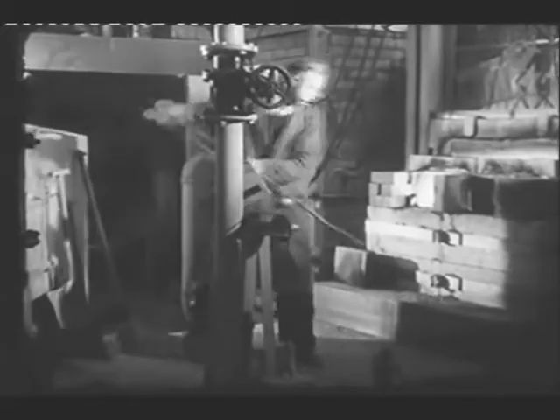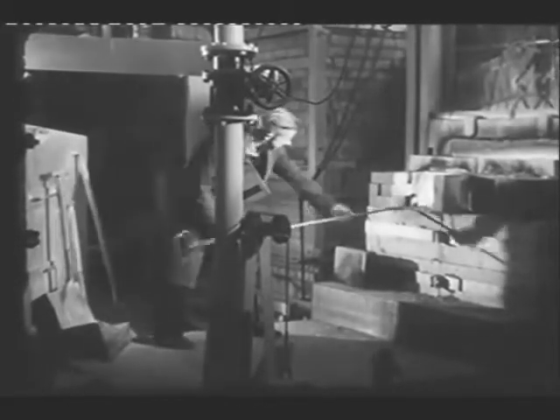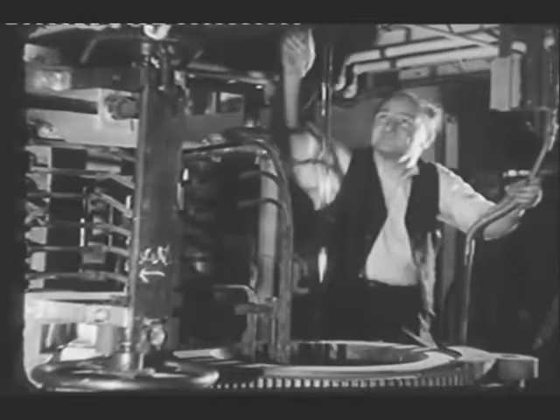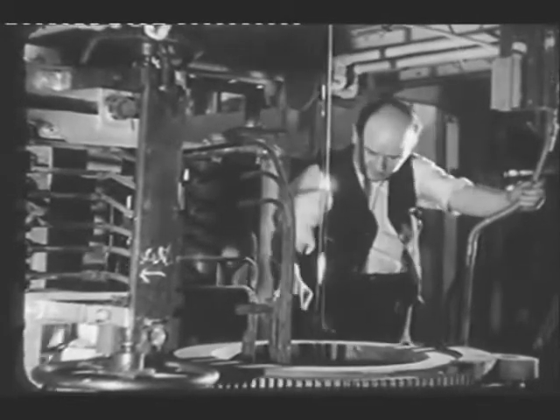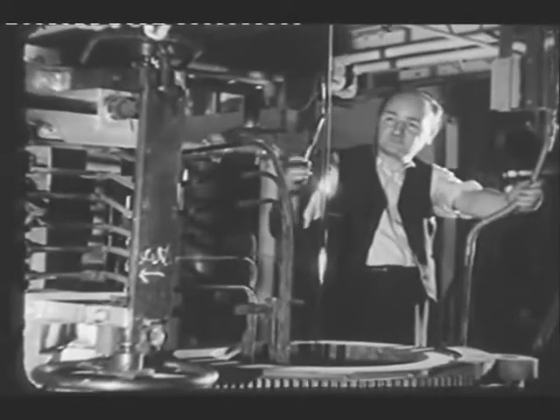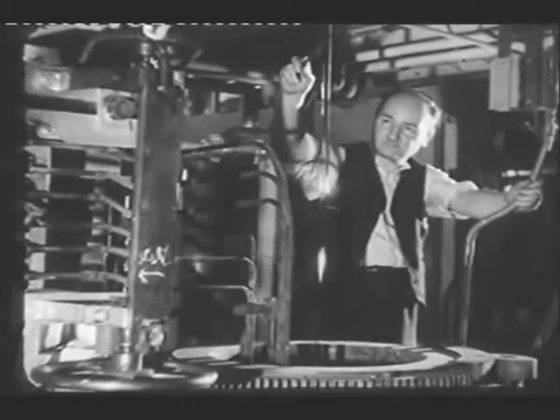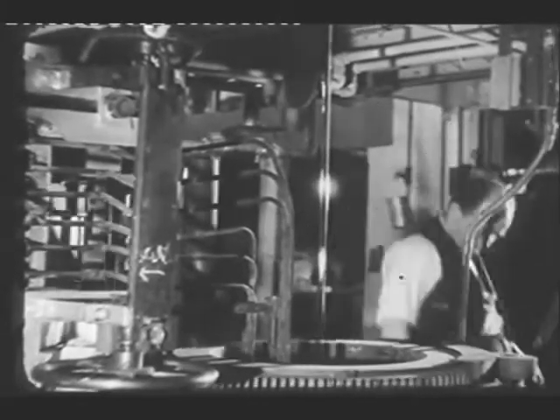Here are the raw materials of glass: sand, red lead, soda, and a proportion of broken glass, technically known as cullet, which are melted together in the glass furnace. Many of the glass parts used in valve manufacture are made from glass tubing. From the tube-making machine, a column of molten glass is drawn upwards, an internal blast of air keeping the glass in tubular form and controlling its diameter. As it ascends, external air streams cool it and control the thickness of the wall.